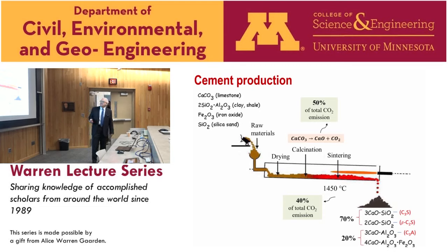In the process of making the clinker, one of the first steps is decomposition of calcium carbonate, or limestone. As you can see, we get lime that becomes a vital component of the calcium silicate type of binder, which Portland cement is, and we are emitting CO2. The final product contains about 70% of those calcium silicates.